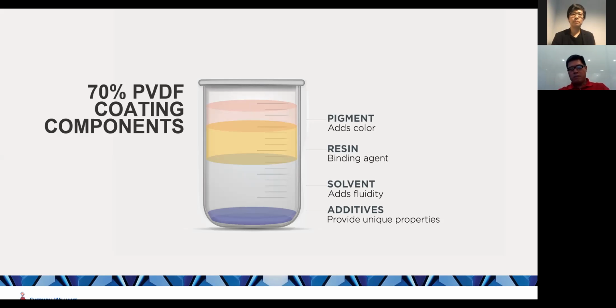Solvent is the thinner that makes the pigment and resin easier to apply and provides application properties. So let's say for the coatings that we use for our walls at home, that's consumer paint, and the solvent here is water. So we adjust that material to the right viscosity so that we can apply it. We can roll or brush it onto our walls. But for coil coating and extrusion coating, due to this different application process, we have to adjust our coatings to a different viscosity to fit that process. Okay, so that's the solvent part of it.